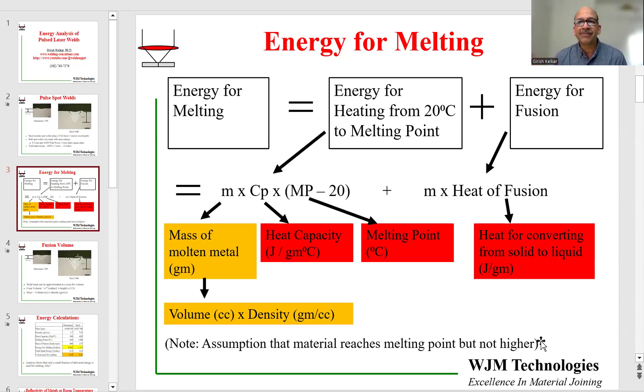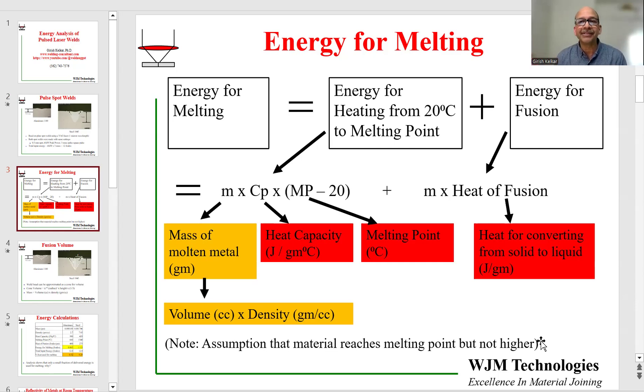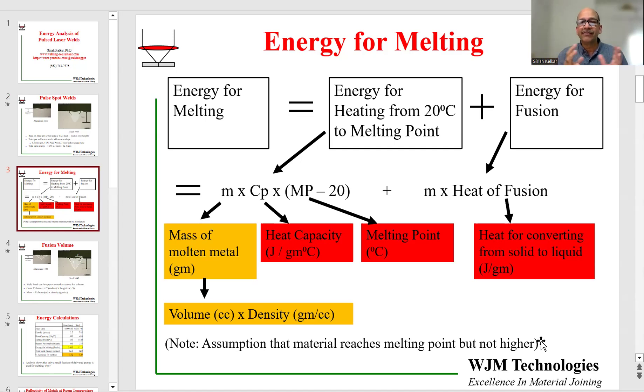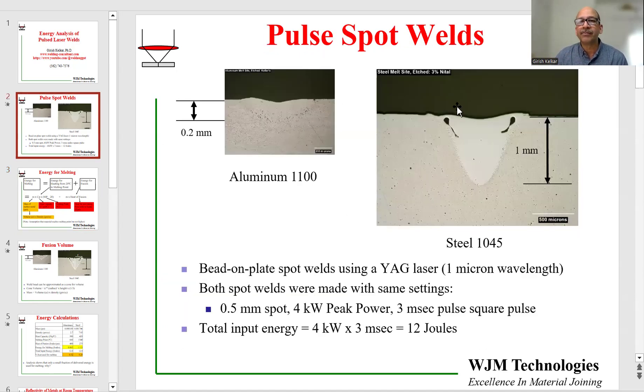That's not entirely unreasonable, because during the heating process the temperature increases, and once melting starts, heat is transferred down into the bulk producing a volume of molten metal. That molten metal, even though at high temperature, is also quickly losing heat by conduction, which keeps the molten metal from going too high in temperature. Of course it still depends on peak power — if it is very high, you can get boiling and spatter. In this case we did not get a lot of spatter, though it looks like it might be on the verge based on these swirls, which are porosities formed due to that swirling effect.